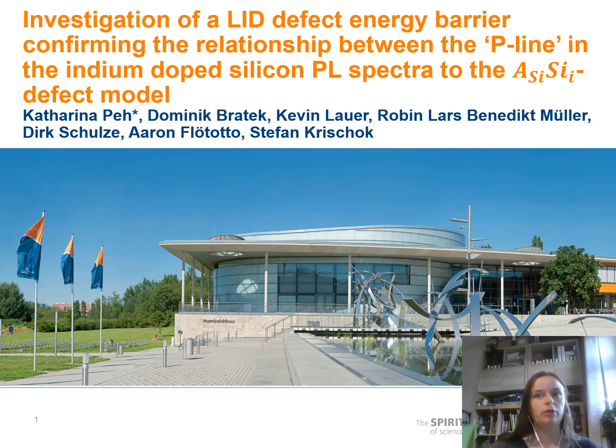from Ilmenau, Germany, and I would like to present our latest investigations of the LID defect in indium-doped silicon. We use an excitonic photoluminescence line, the P-line, that changes its intensity through illumination and annealing steps to determine an energy barrier of the defect using low-temperature photoluminescence.